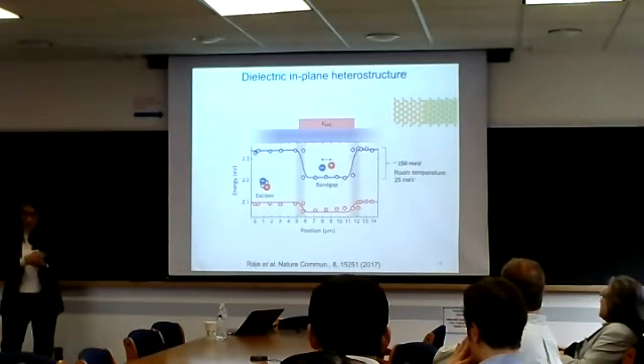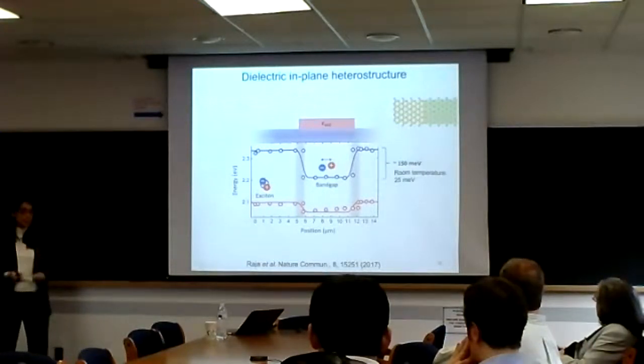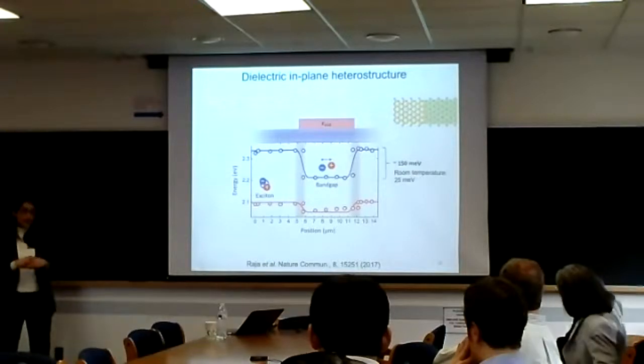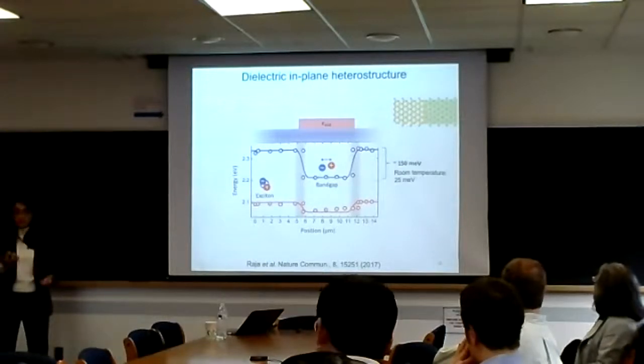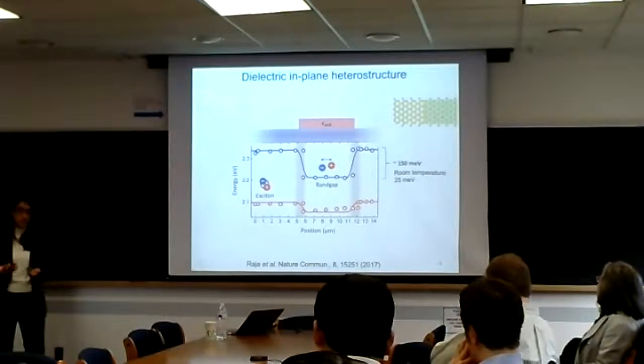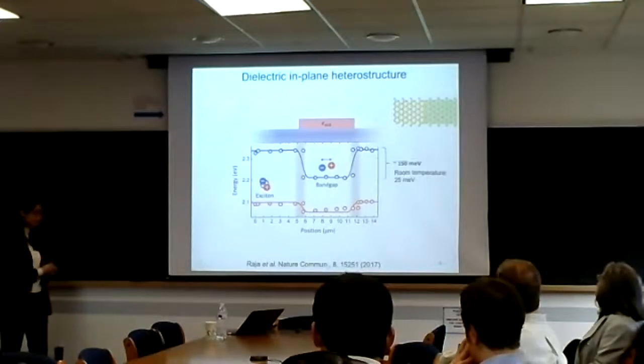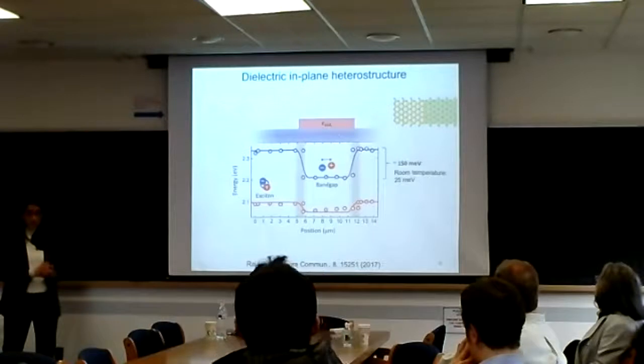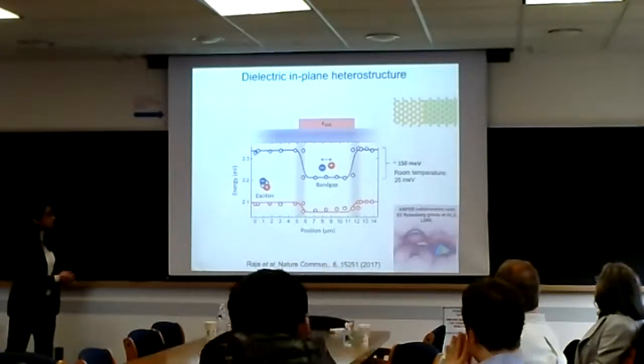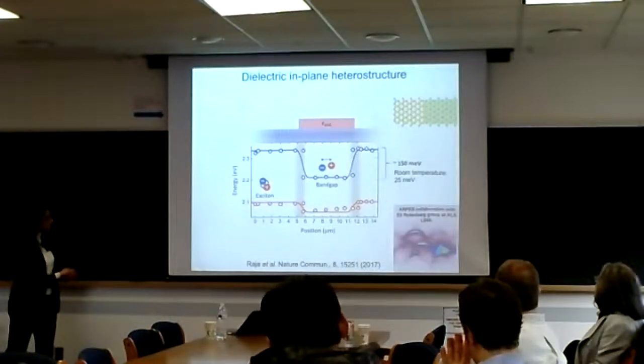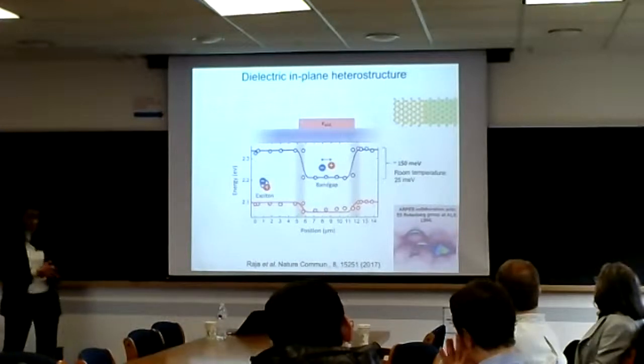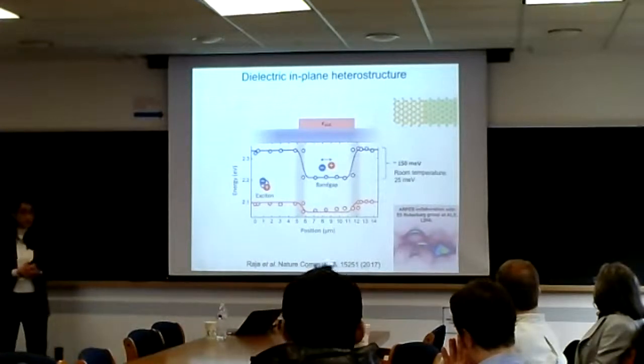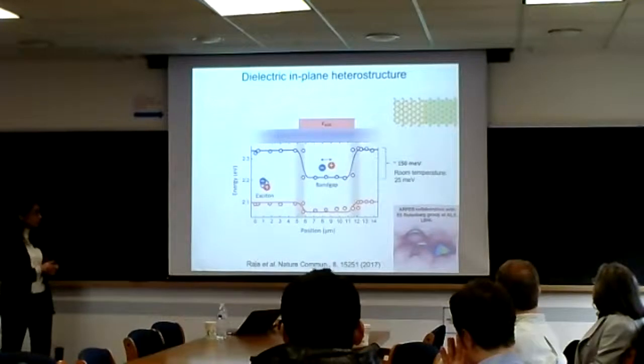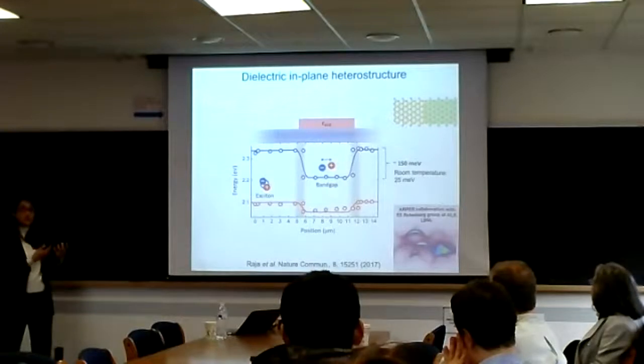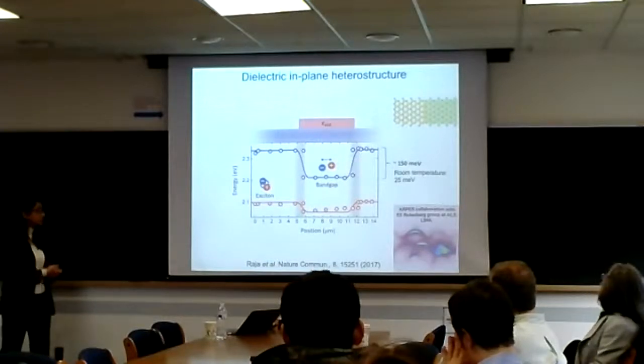So I talked to you about the vertical transitions in these materials, which relate to just the band gap, but I was suggesting that this is non-invasive, that you're not really changing the band structure. What's the evidence for that? There's no direct evidence from the optical spectra that I have here. So what I decided to do when I moved to Berkeley, because they had this very nice user facility at LBNL, Lawrence Berkeley National Lab, was angle resolved photoemission with spot sizes comparable to far field optics.